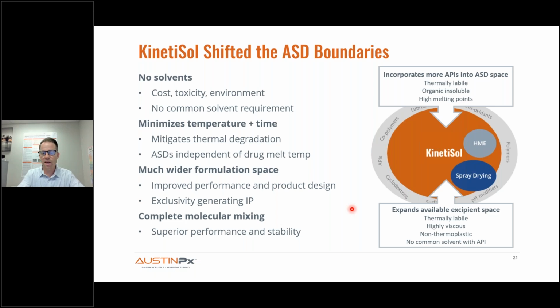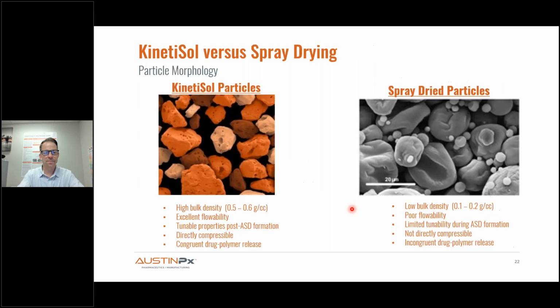And this slide just illustrates some of the other advantages. Obviously, kinetisol requires no solvents, so I think we know what the benefits are there. I've already talked about minimizing thermal exposure. This slide demonstrates the much wider formulation space. And then when you talk about the mechanism of formation, as I've described, it's solubilization of crystalline drug in the molten polymer, a dissolution process. We get above the Tg of the polymer through mechanical energy. We don't add any external heat. It's mechanical energy that changes the polymer itself into a more malleable, flexible, fluid-like state, and that acts as a solvent for the crystalline drug. And so we're dissolving crystalline drug within the polymer. So it's like a dissolution process where you're spinning that dissolution paddle really, really fast. So we're solubilizing that crystalline drug within seconds.